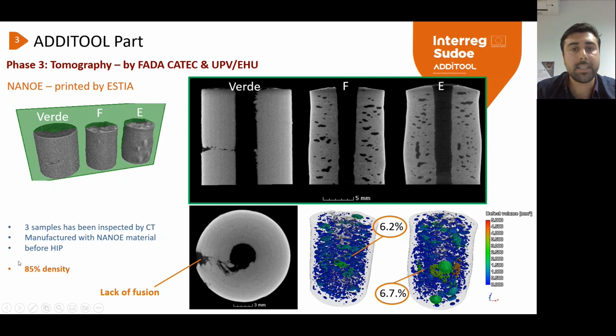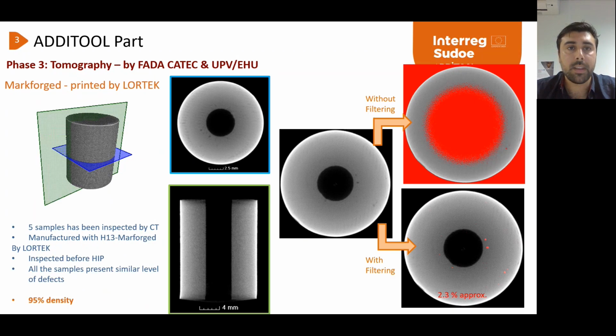Not so easy to print. You have a little bit of clogging of the nozzle on one layer. You have some deformation, etc. So you have a lot of porosity inside, and the mechanical properties are very poor.